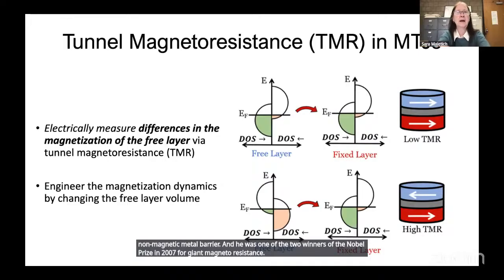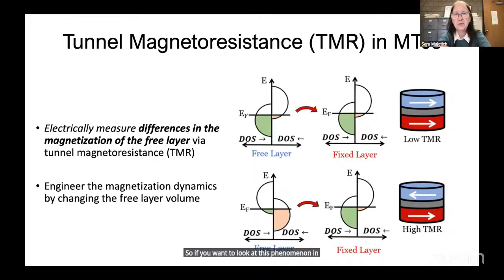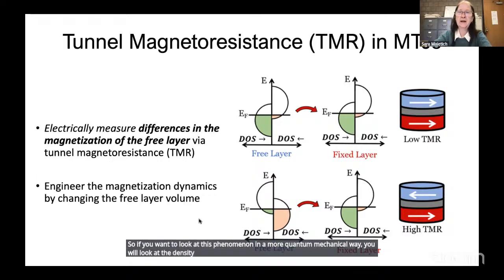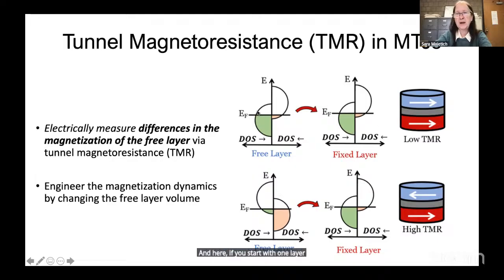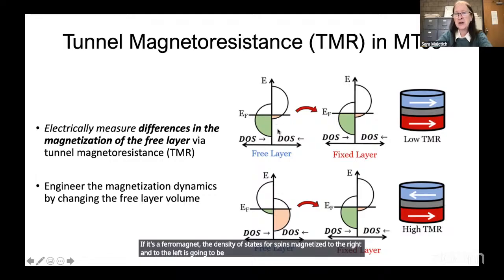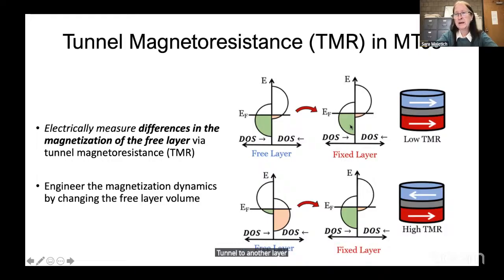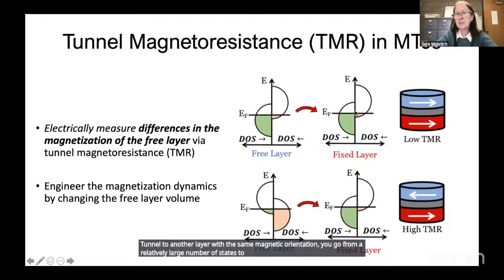So if you want to look at this phenomenon in a more quantum mechanical way, you will look at the density of states between the different layers. And here, if you start with one layer that's magnetized one way, if it's a ferromagnet, the density of states for spins magnetized to the right and to the left is going to be offset by the exchange energy, and there can be different numbers of available spins at the Fermi energy. If you go to tunnel to another layer with the same magnetic orientation, you go from a relatively large number of states to a large number of empty states. So there'll be a lot of current.